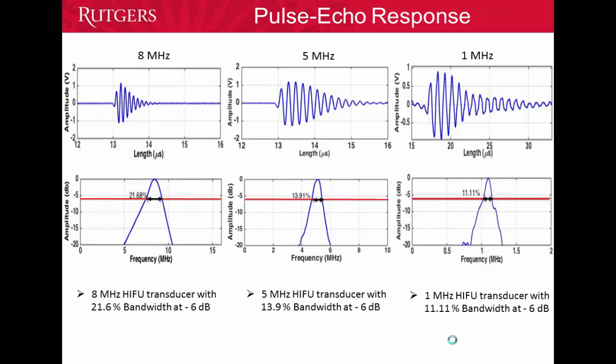We measured the pulse-echo response. Obviously, you can see that at 8 megahertz, we have a minus 6 dB bandwidth of 21.6%. At 5 megahertz, we have a minus 6 dB bandwidth of 13.9%. And at 1 megahertz, we have a very low bandwidth of 11.11%.